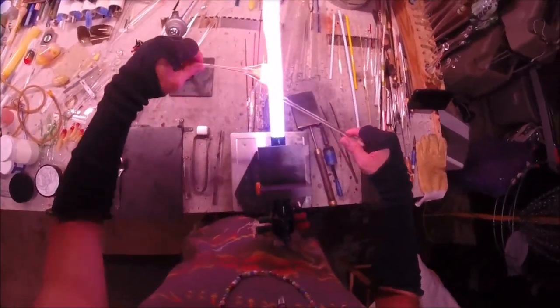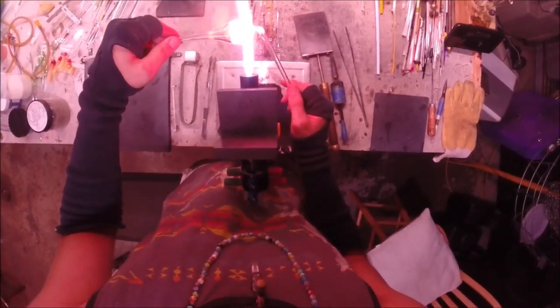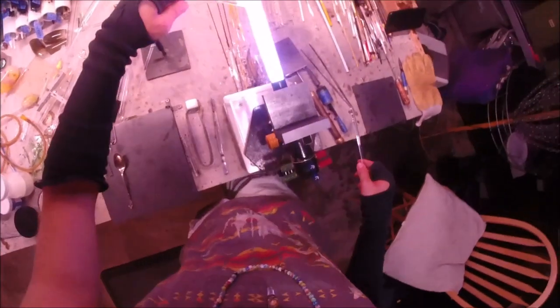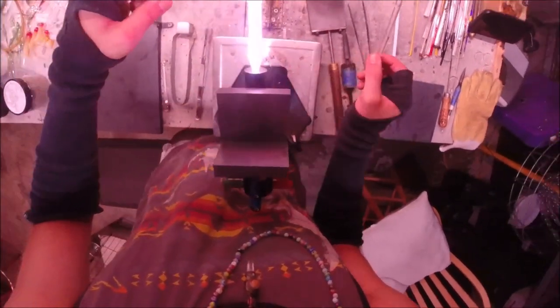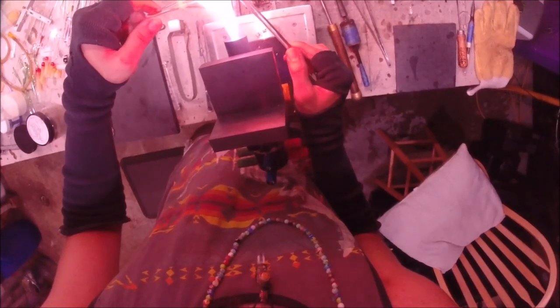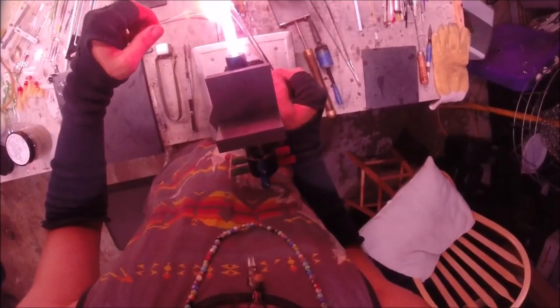Now I'm working a little bit more on removing some glass at the tip there, slowly rotating the rod in my right hand as I touch the center of the pendant — it'll draw all the dots towards the center. When you're cleaning up a termination on one of these, you really want to make sure you have enough glass hot that you're pulling the dots towards the center and not just removing glass from the center, or else you're not going to get the same kind of visual effect that you want — kind of like flower petals pulling in from the middle of the pendant. As I condense this and tighten up all the dot work, I'm going to keep removing glass at the termination just to make sure it's crispy and comes to a nice point in the center.